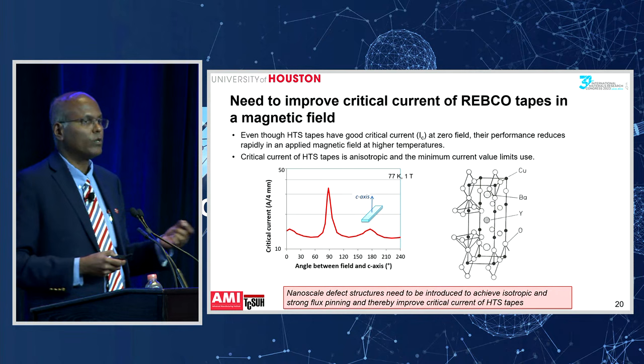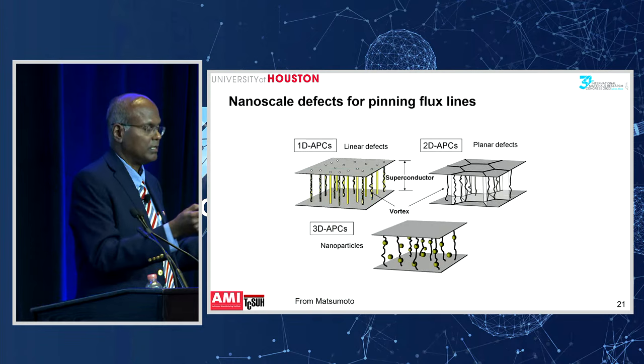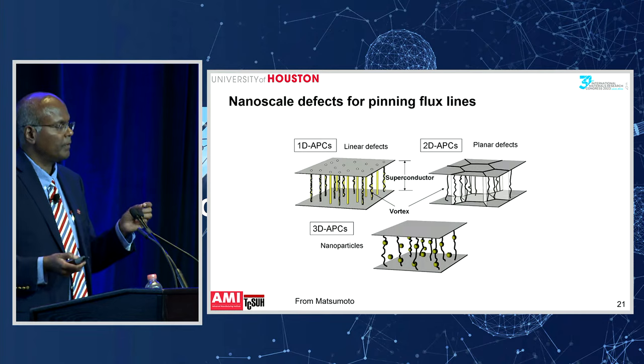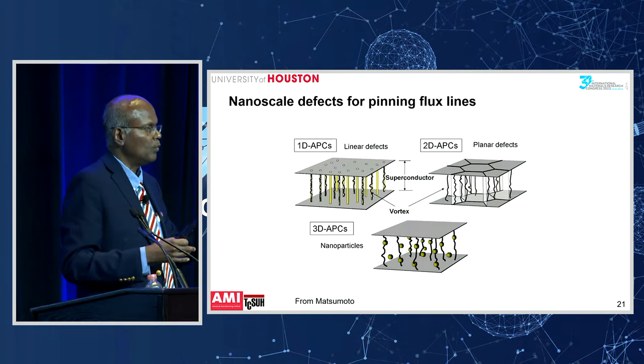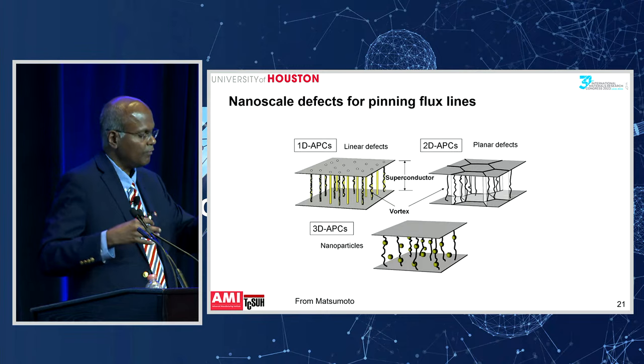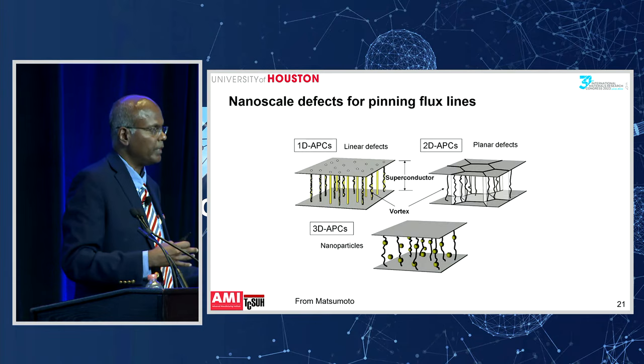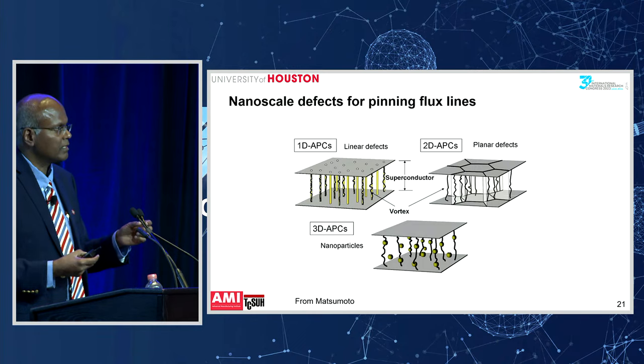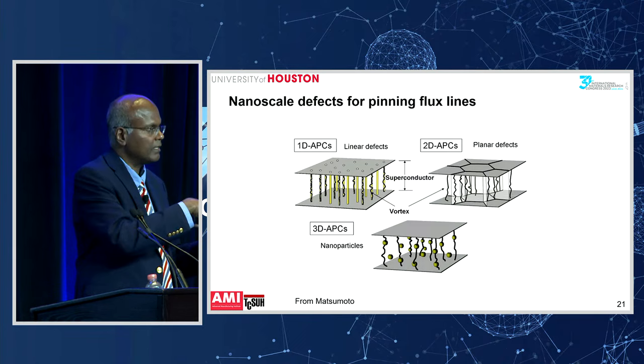So the case of superconductors is somewhat different from semiconductors. In semiconductors, you want to avoid defects, whereas in superconductors, you actually like to incorporate defects. The reason is that when you apply a magnetic field, the magnetic flux lines or vortices penetrate into the superconductor, and once they penetrate, when you flow a current, the Lorentz force will make the vortices move around, and that will dissipate energy, and this material will not be able to carry much current. However, if you introduce defects, it is energetically favorable for the vortices to penetrate the defects rather than the superconductor, so they get pinned and held by these defects.